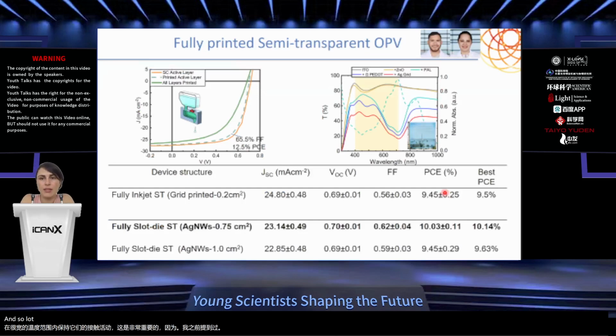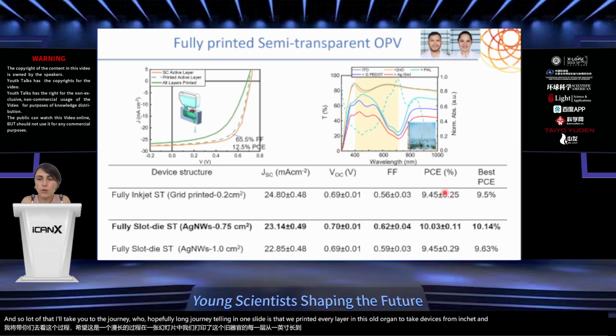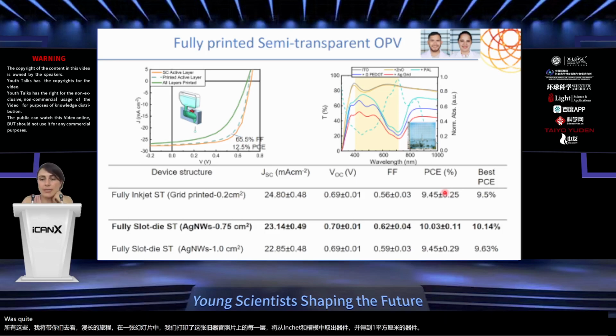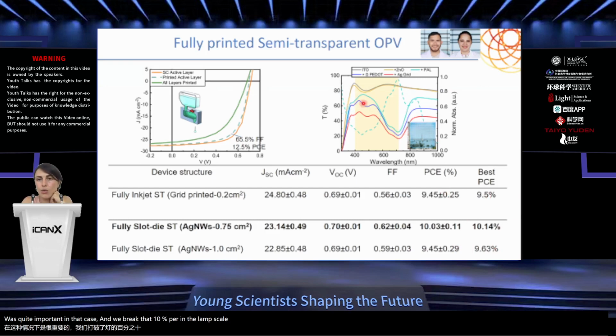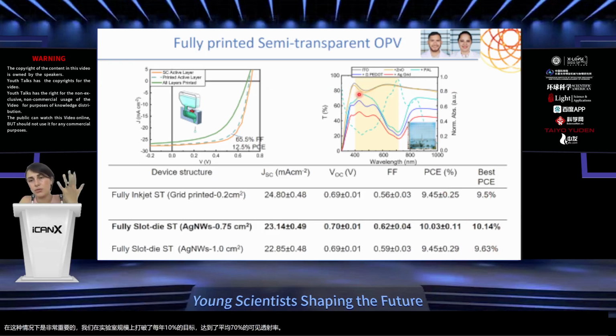So out of that, I'll take you to the journey, actually a long journey, told in one slide: we printed every layer in these organic photovoltaic devices from inkjet and slot die as well, and achieved 1 square centimeter devices, which was quite important in that case. And we broke that 10% barrier at lab scale, achieving over 70% average visible transmission just for the photoactive layer, and for the whole devices around 50%, which was quite interesting.